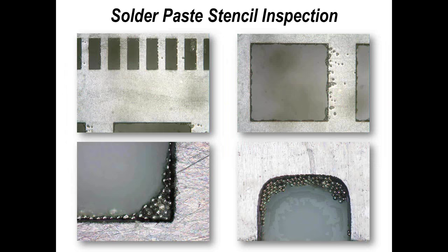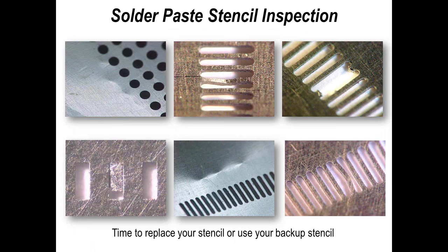So consequently, during reflow in air, you get poorer results. So regular cleaning of the stencil, and possibly offline cleaning as well, or using manual ultrasonic cleaning can improve the cleaning performance of the stencil. Now, damage to stencil is pretty straightforward, but still when I do audits of companies, I quite often see stencils that are damaged. These are what I would consider very severely damaged, but any damage to the stencil will impact the quality and consistency of the printing process. So it's good practice to have a backup stencil of any design that you're running, because it is easy for me or any engineer to damage it. So just consider having backup stencils.